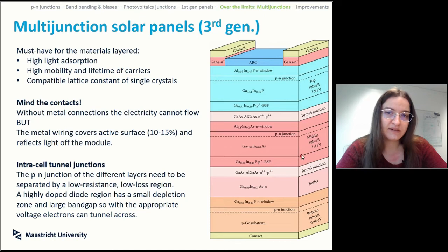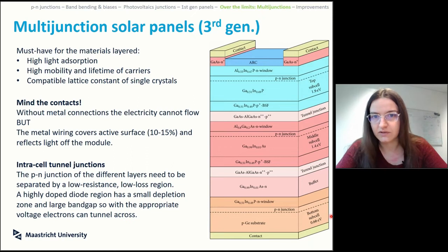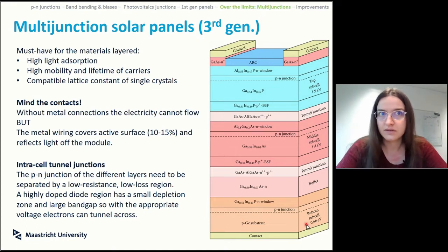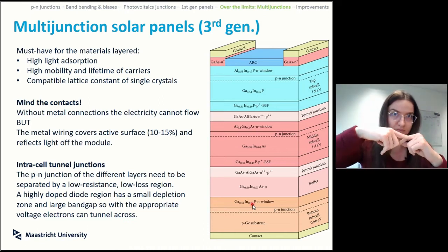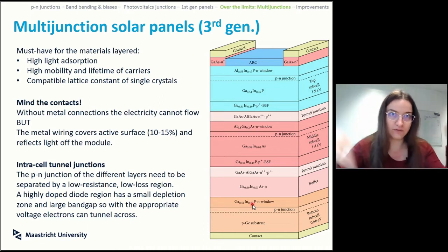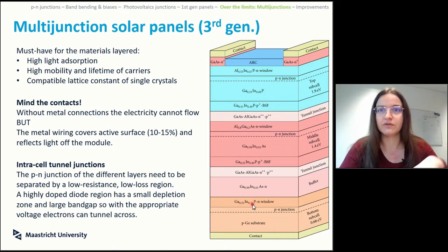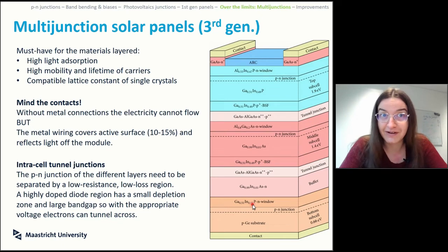Then you have another point with another tunnel junction, in which you have your bottom cell at 0.66 electron volt, so anything between 0.66 and 1.4 gets absorbed down here. Anything that is below 0.6 is not absorbed, it just doesn't go through. You lose that energy because there is nothing able to absorb it. And you have your point of contacts, meaning that the electricity will actually get generated but get off following the bias that you imposed.